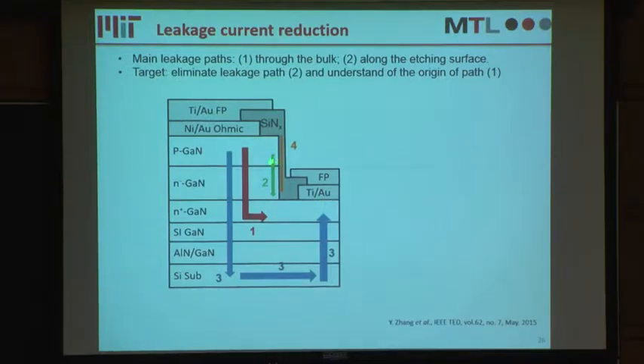The second one is a leakage path along this etching sidewall. Because this mesa structure is typically fabricated using very high energy dry etching, this dry etching can induce a lot of damage and defects at the etching sidewall, so there might be a leakage path along this sidewall.